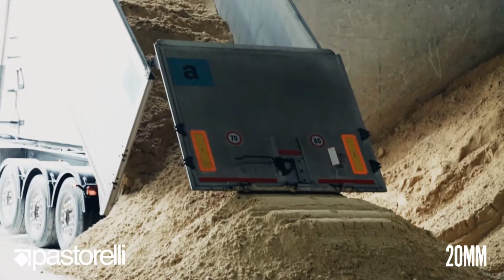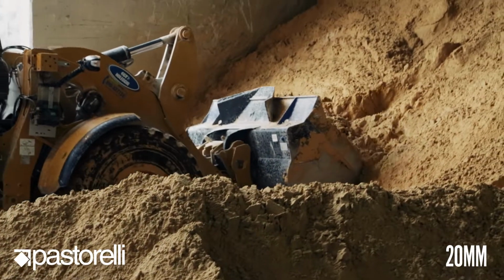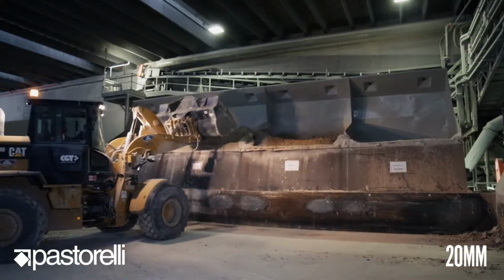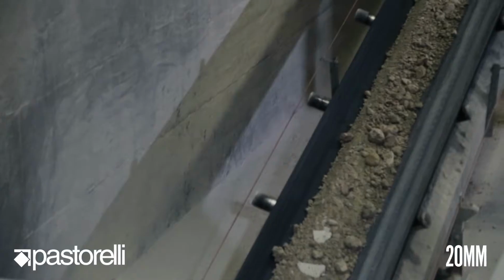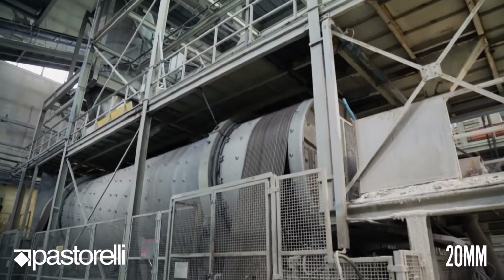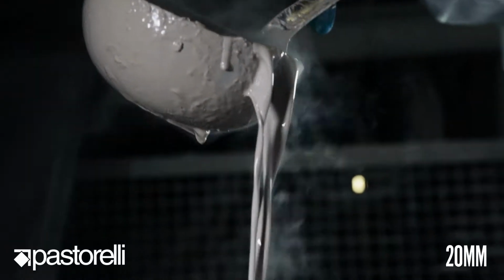20 millimetri 2 cm thick porcelain pavers are produced with natural, inert raw materials. Clay, feldspar, a mineral containing quartz, and sand. The various components are automatically mixed in the right proportions, like the ingredients to prepare a cake. A conveyor belt carries the raw materials to the mill. Water is added, and the raw materials are ground into tiny particles using heavy spheres made of alumina, a hard ceramic product. The result is a milky liquid called barbotina.